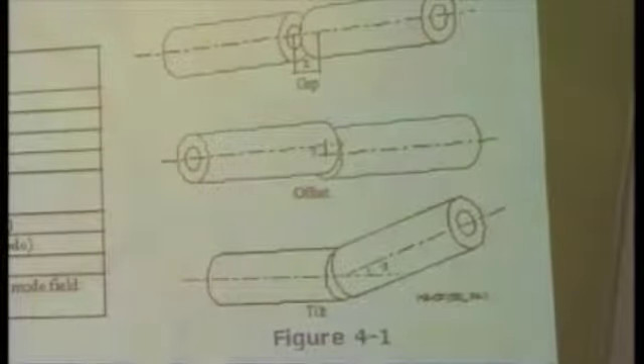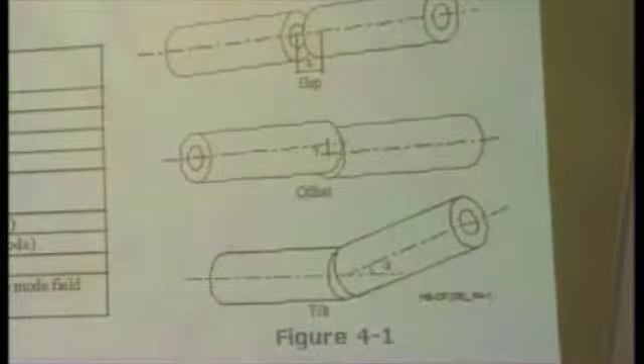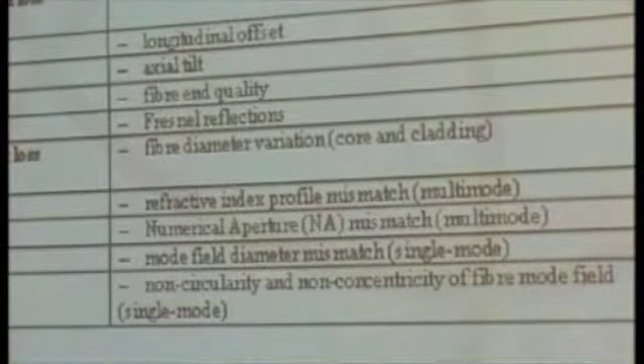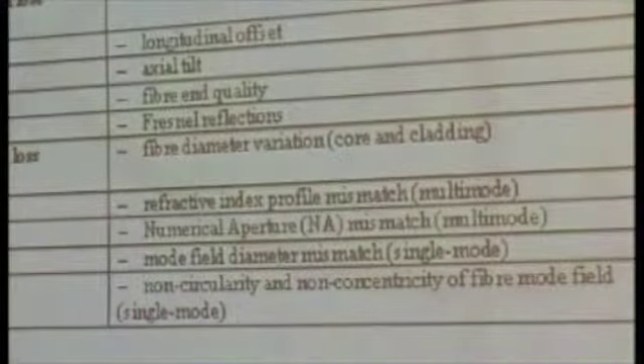On the other hand, there are some factors that are directly related to the fiber. If one fiber has some diameter variation, considering the core, that's the central region, or considering the cladding, when both are put together we can find a discontinuity. As this is caused by the fiber characteristic, not by the fiber position, it is considered intrinsic. Another kind of factor that could cause loss in splicing, mainly in multimode, is the refractive index profile mismatch. We need to have an index profile to have the light guided inside the fiber, and if there's a big difference between one fiber and the other, it causes loss.